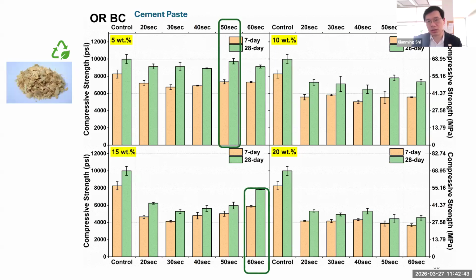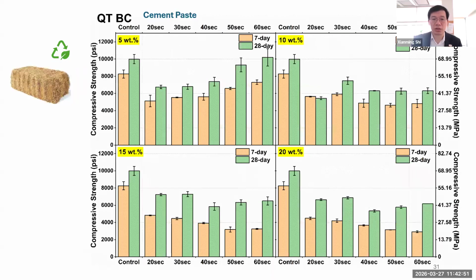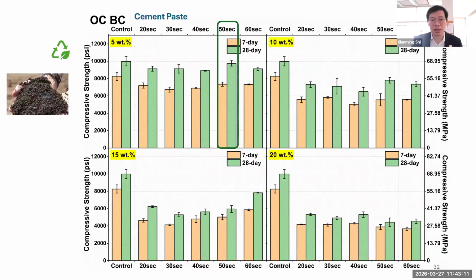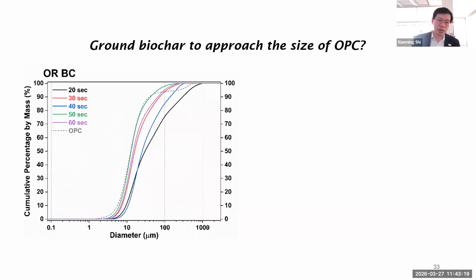So in a nutshell, we see higher strength when we grind 50 to 60 seconds for this Oregon biochar, and for the next one, it's about 60, and in some cases 30 seconds, which is a little surprising. But again, when you add so much, 20% replacement of cement, you do see significant reduction compared with the control in terms of strength, even though they're still well above 5,000 psi. Now, here's another one, again, 50 or 60 seconds. And what does this mean? We see grinding for different amounts of time. Basically it's getting finer and finer until it approaches the size of ordinary Portland cement particles. So the assumption or the observation is that when you grind it to such a degree, it's very similar in terms of size gradation to the ordinary Portland cement. They induce better products in the end.